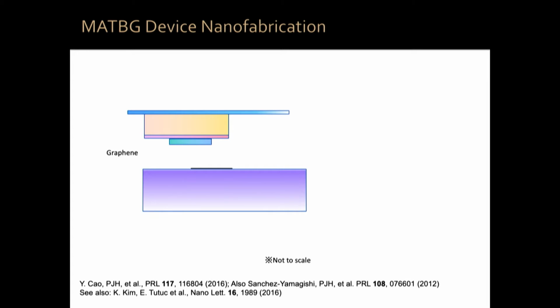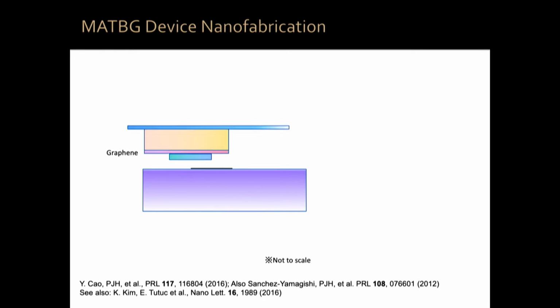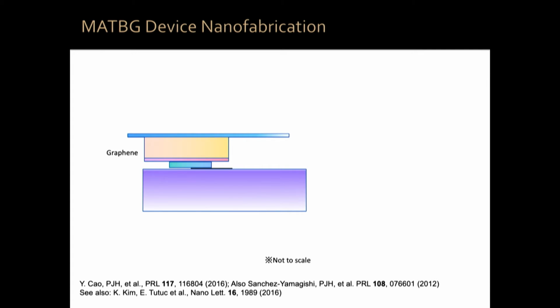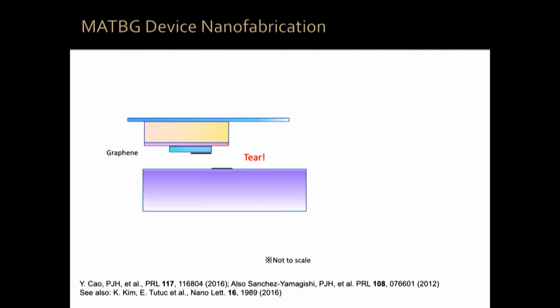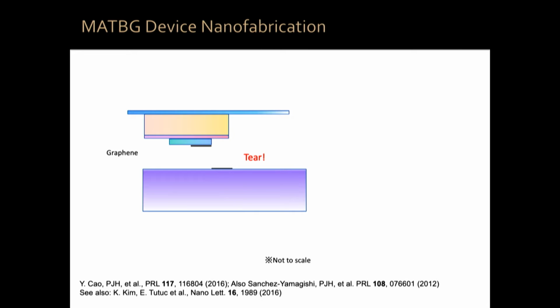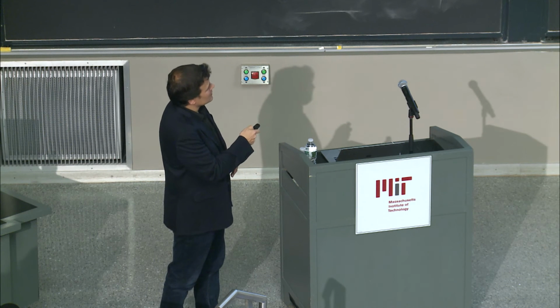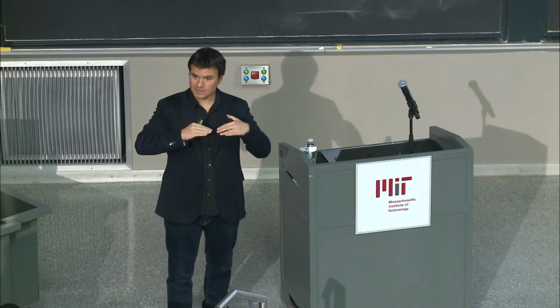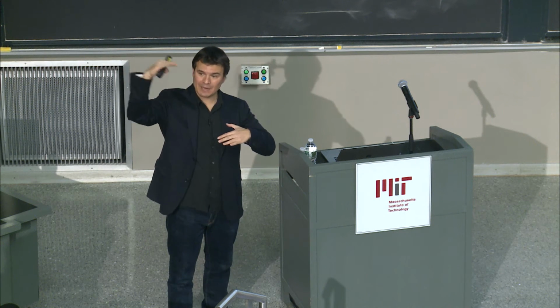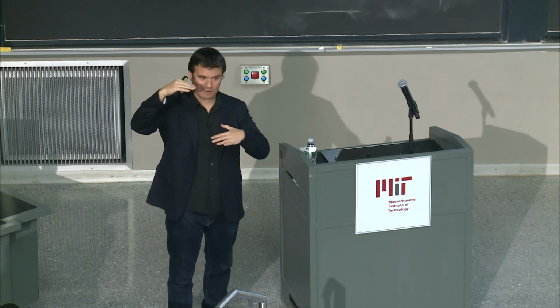Hundreds of groups around the world can do this. And then we position our hexagonal boron nitride sort of halfway on top of it, okay? Then we bring the boron nitride down and we tear this half piece of graphene, okay? Now, because these two pieces come from the exact same crystal, even though they're at different heights, they maintain registry in terms of crystallographic alignment.